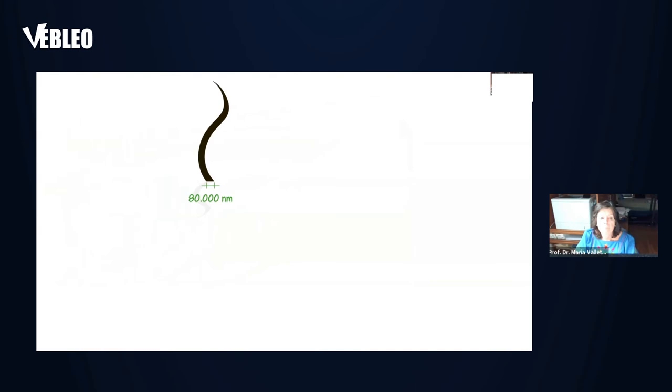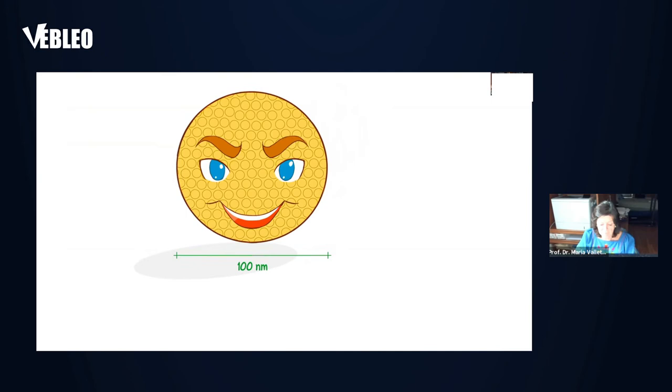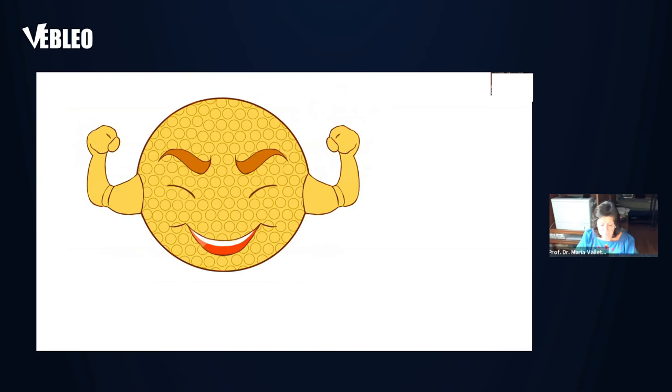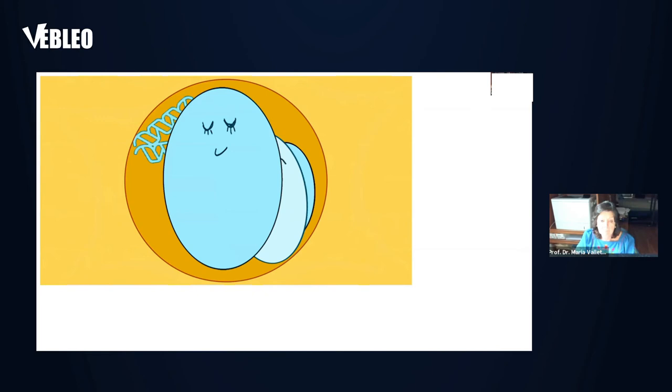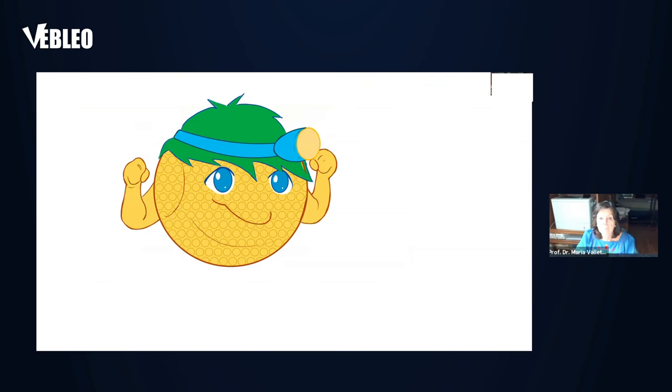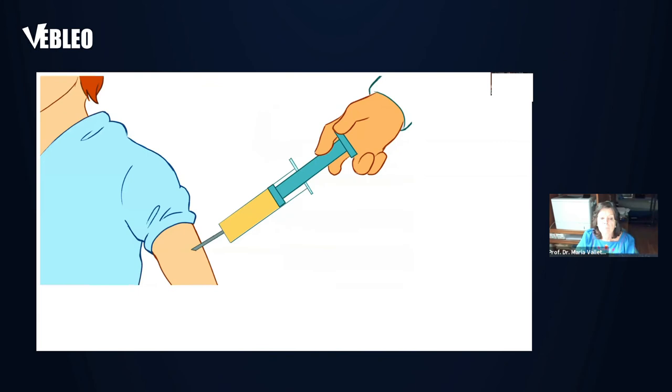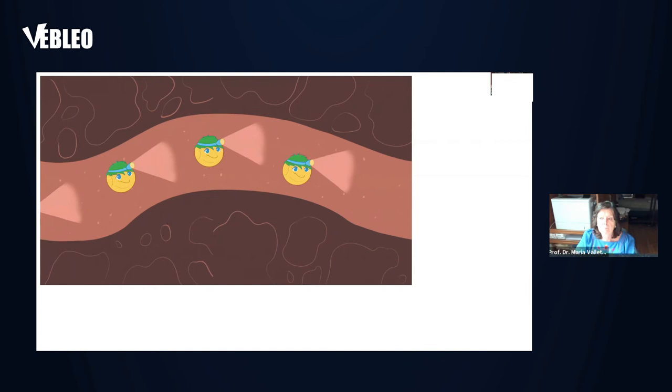Mesoporous silica nanoparticles are extremely small, about 800 times smaller than the thickness of a single hair, and they have plenty of pores, around 1,400 pores per particle. These pores are about 2 or 3 nanometers in diameter and about 100 nanometers in length, so they can hold many antibiotic molecules, as each antibiotic molecule measures about 1 nanometer or less. The group of Professor Maria Vallet-Regí is focused on loading the pores of these nanoparticles with pharmaceutical drugs, while modifying the external surface of the nanoparticles with guiding molecules able to drive them towards the infected area with total specificity. The drugs are loaded inside the pores. Its surface can be modified by anchoring molecules able to direct them to the bacteria colony of the biofilm where they act.